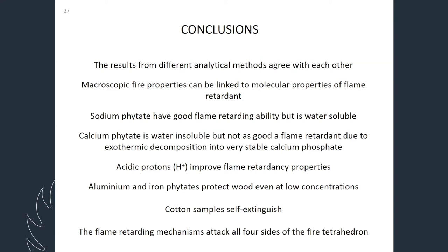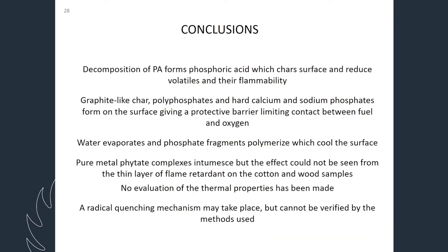Aluminium and iron phytates, we had only a tiny amount of aluminium and iron, but we still had flame retardant properties. We can see that the cotton samples self-extinguish rather than burn like the untreated ones. And the flame retarding mechanisms seem to attack all four sides of the fire tetrahedron as we have predicted.